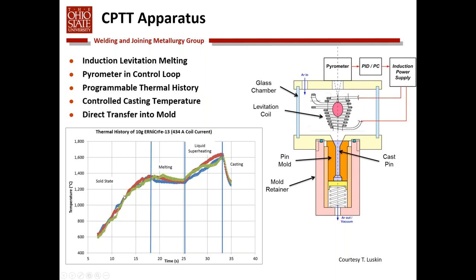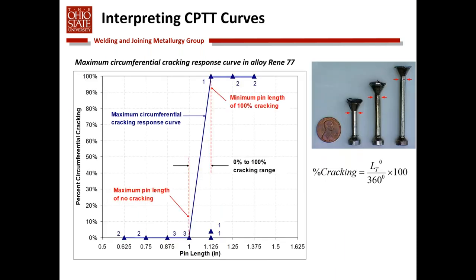And then we run along a program that basically heats it to the melting temperature, provides a little bit of superheat. This is for a nickel base alloy. We would take it up to about 1600 degrees centigrade. And then basically we dump it into a mold, a copper mold, as shown here. And again, we can vary the length of this mold to vary the amount of restraint.